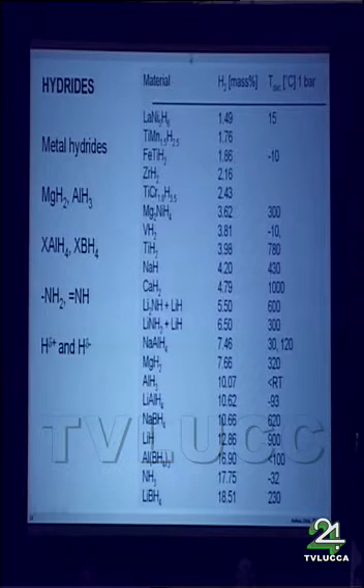Now, I would like to say some words about the challenges of new systems. Here is a list of hydrides, and there are a few things I would like to point out. This list starts with lanthanum nickel 5 H6 with 1.49 mass percent of hydrogen. It goes up to lithium boron hydride with 18.51 mass percent of hydrogen. So you can see that's about the limit. We do not know materials which show a higher mass percentage of hydrogen than 18.5. And in between, for almost any value, we can find a corresponding hydride.